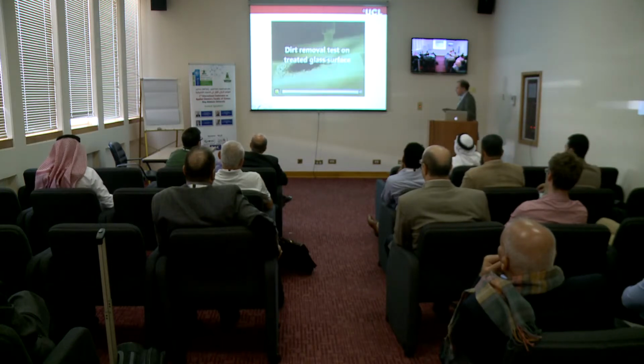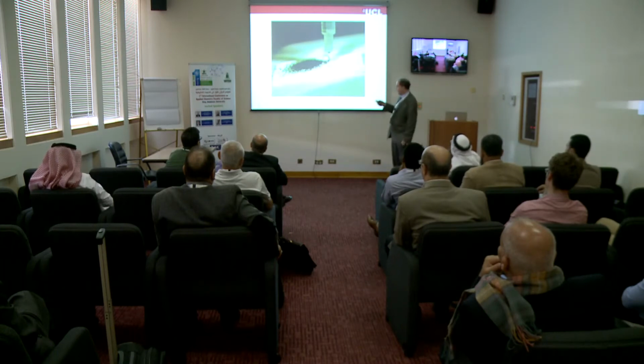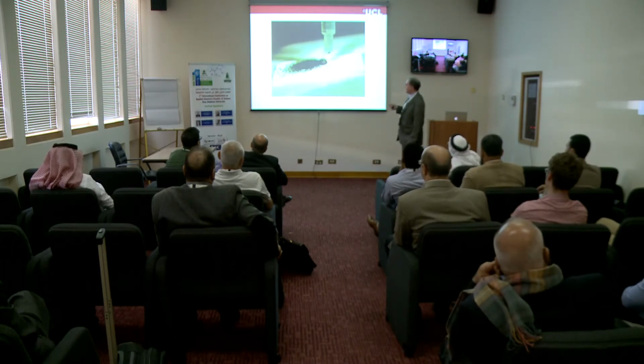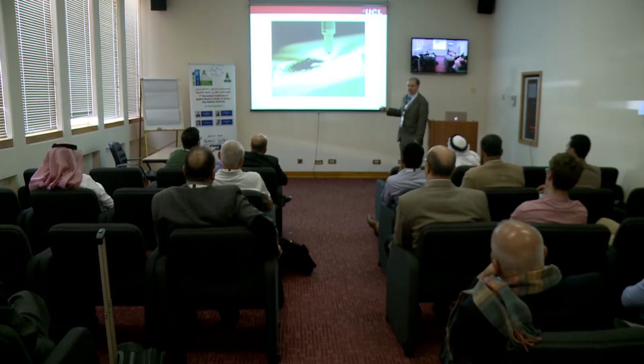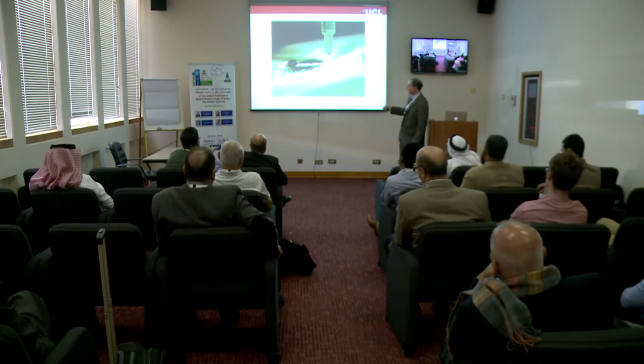So this shows a dirt removal test. This is a super hydrophobic surface, and on that surface you see another water droplet, and this is simulated dirt which we put down. I talked about the rolling motion. This rolling motion of the water droplet acts as a miniature vacuum cleaner, and it sucks up all of the dirt from the surface, and you can see that there's a clear path afterwards where the water droplet has moved. So this is really good for being able to clean dirt.